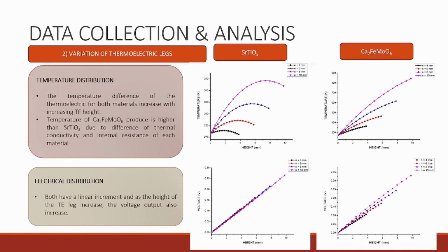Variation of thermoelectric legs. For the temperature distribution, the temperature difference of the thermoelectric for both materials increases with increasing height. The temperature of calcium iron molybdate is higher than strontium titanate due to the difference in thermal conductivity and internal resistance of each material. For the electrical distribution, both have a linear increment, and as the height of the TE leg increases, the voltage output also increases.